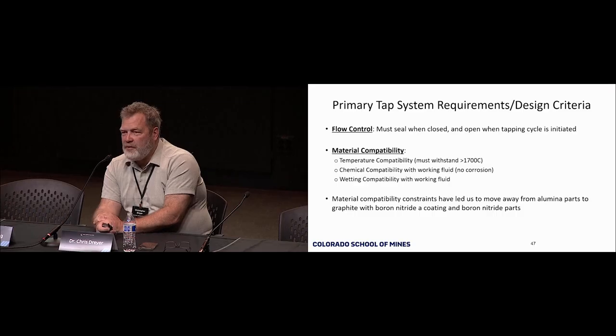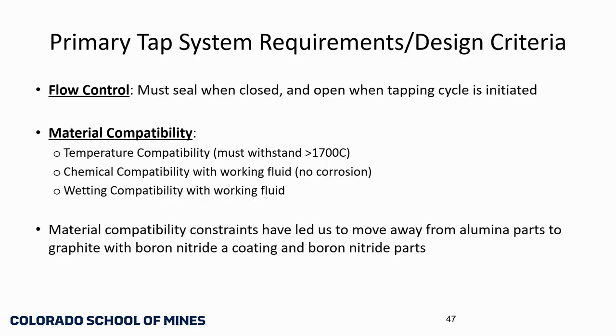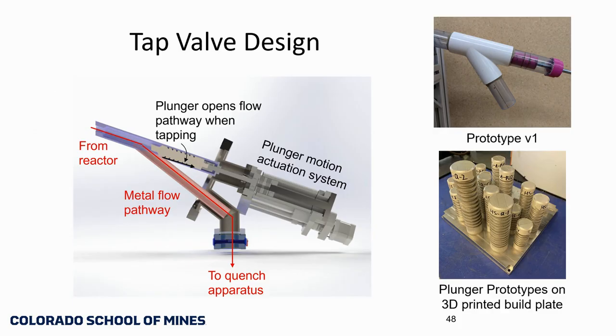We had initially thought we were going to use alumina. It has the best material compatibility, but actually has poor thermal shock behavior. And we've done some testing where, when molten aluminum flowed through it, it just shattered instantly. I can show you some of the results of that in our show and tell. So we're moving to graphite, which has poor chemical compatibility but good shock characteristics, and plan to coat it with boron nitride to protect it and have better compatibility. There may also be some boron nitride parts we'll work with. This is our tap design. There is a plunger that moves through the Y joint, from the reactor to the transfer point down to the quench apparatus.